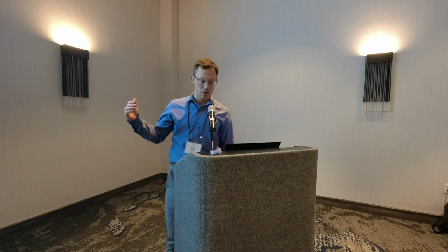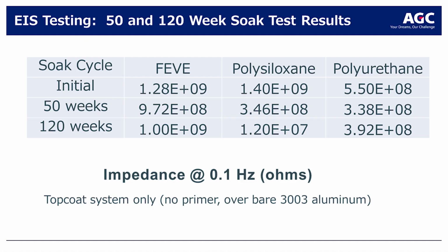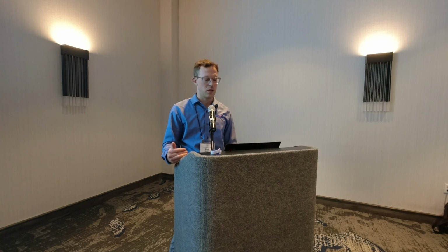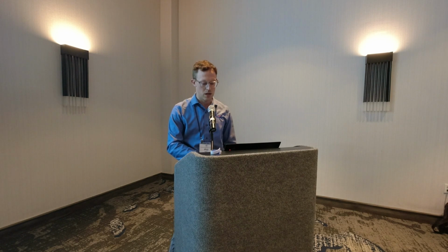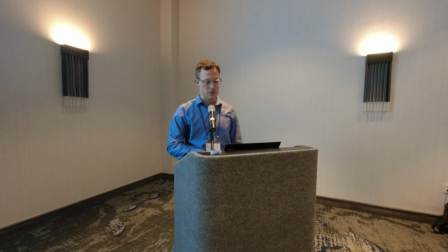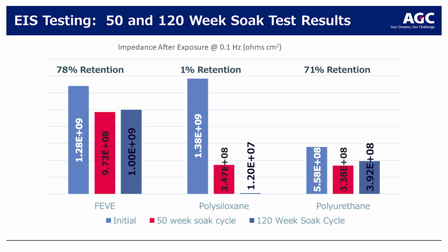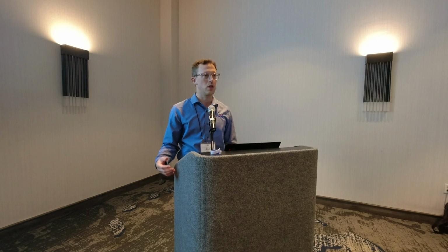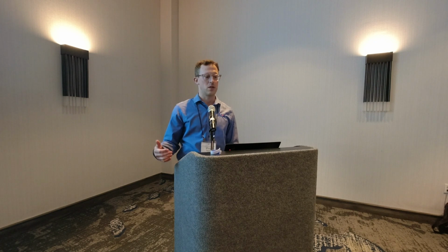So these are the figures that we measured at the impedance of 0.1 hertz. If you look at the different soak cycles for 50 weeks and 120 weeks, you see a pretty similar result initially, but after you spend time, you definitely see Lumiflon maintaining its performance, and you see the polysiloxane and the polyurethane trending down over time, with a reduction in their corrosion resistance. This is that last one visualized, just to make it a little easier on the eyes. That's what we're seeing within our electrochemical impedance testing, to say, yes, we are confident that this is going to help with corrosion when you're painting your surfaces with this technology.